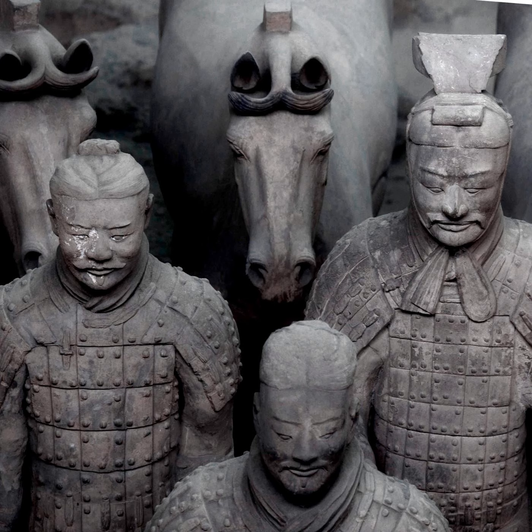But the interesting thing is that because you're losing a component of the molecular structure of the clay, your clay actually shrinks at this stage instead of expanding. Even though it's getting hotter, it gets a little smaller because you're losing a component of the structure of the clay, which was the molecular water. So this process of ceramic change happens between the temperature ranges of 350 degrees Celsius all the way up to about 700 degrees Celsius, or from 650 to 1,290 degrees Fahrenheit. Hot stuff.